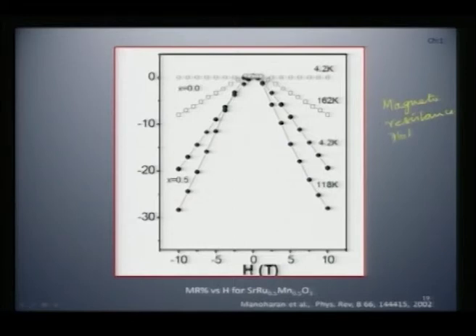Magnetoresistance plot as a function of magnetic field. So when you sweep the magnetic field in both directions, you will see an enormous loss in the resistance. But what is surprising here is, if you take x equal to 0, that is the SrRuO3 case where there is no manganese, you can see that the MR ratio, the percentage MR ratio at the Curie temperature Tc is only up to 10% approximately, and at 4.2 K